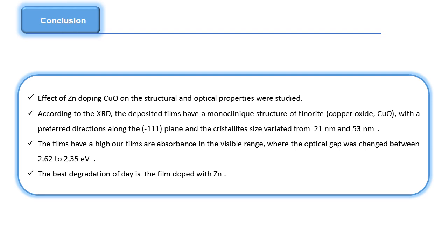According to optical properties, the gap energy varied between 2.62 electron volts and 2.35 electron volts. The best degradation of the dye is obtained with the thin films of copper oxide doped with zinc.